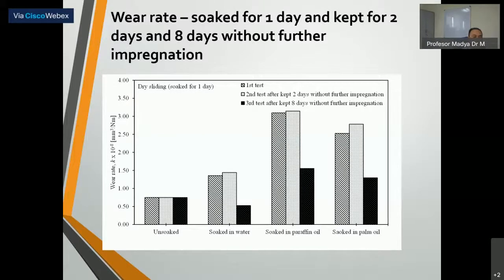Okay, this is the wear rate. We can see that the wear rate is increased after we soak with the lubricant because of the hardness. When we soak with the lubricant, the hardness will decrease.